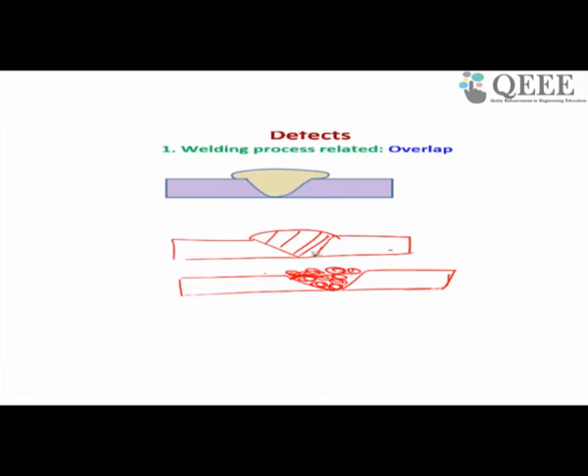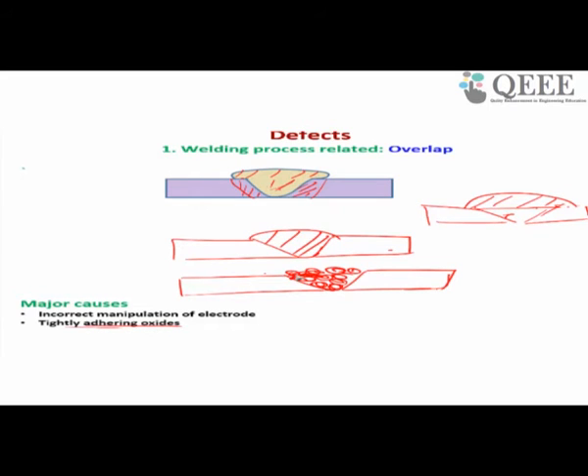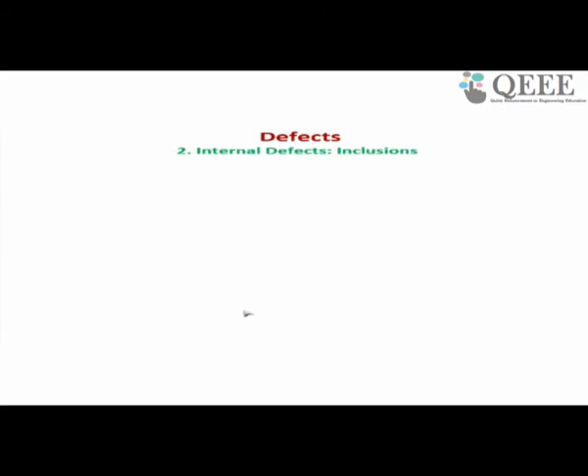For joining this much volume of material, how much electrode will be required, you would have already calculated. Then after joining, what will happen? Because of this oxide layer at the interface, it will not be able to join in this region, but it will overlap the top region like this. If you have this kind of overlapping, you will have heat input again, and it will affect the heat affected zone below this. And as you know, the heat affected zone is the weakest region of your weld material, so it will again hamper the properties. It happens because of tightly adhering oxides, as I said, and incorrect manipulation of electrodes.